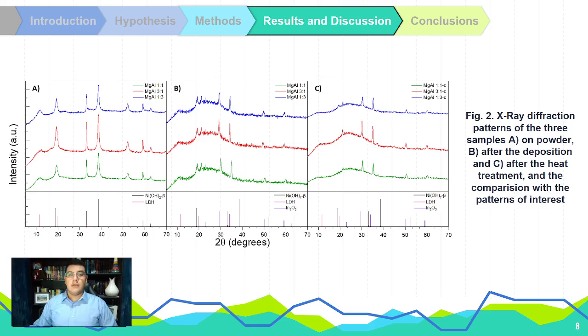After being deposited, we can see the peaks corresponding to our substrate in both the LDH and the nickel hydroxide. However, we notice a decrease in the intensity of those corresponding to the hydroxide. This tells us that the charged surface of the LDH makes the EPD have a preference for its deposition over the nickel hydroxide. Lastly, the diffraction pattern of the calcined sample shows a decrease in all of the signals, but we can see those that would have been expected from the nickel oxide. We conclude that the thermal treatment decomposes our material but doesn't allow it to properly crystallize.